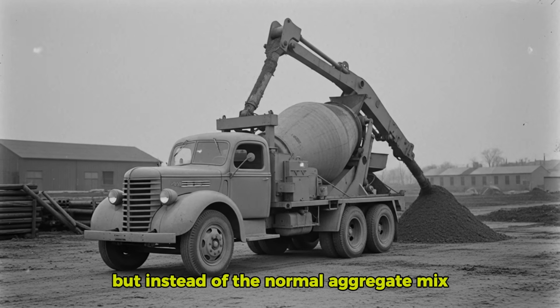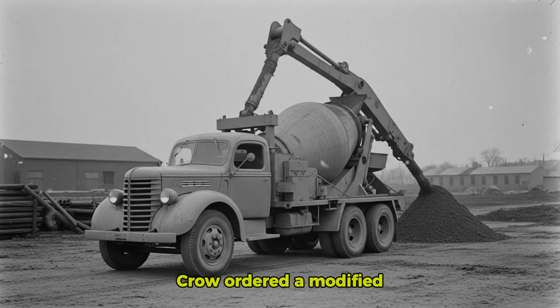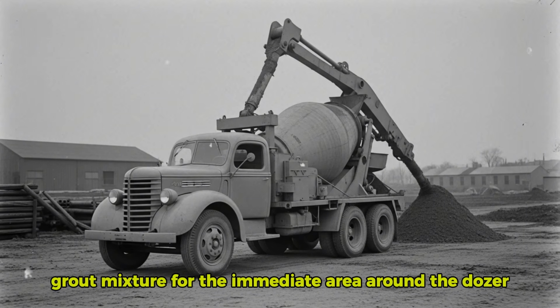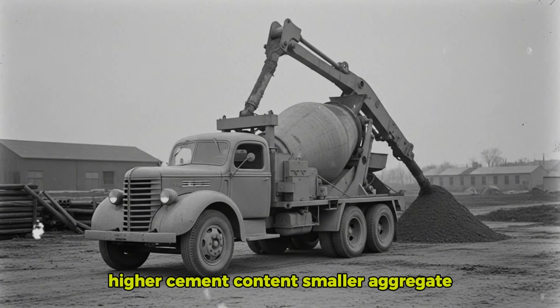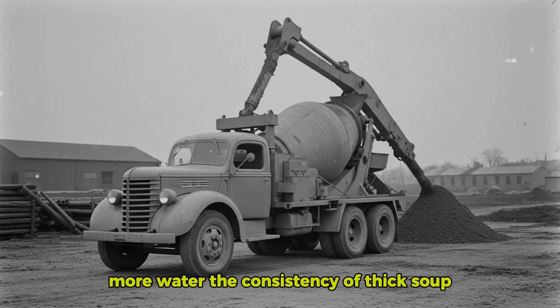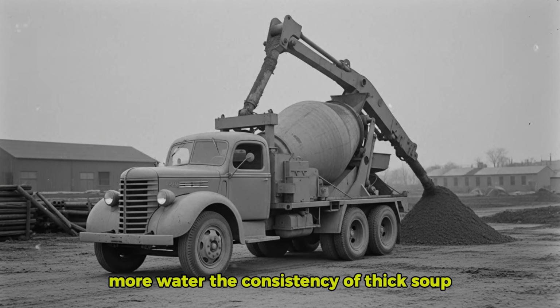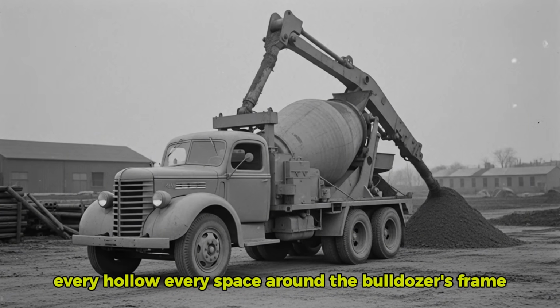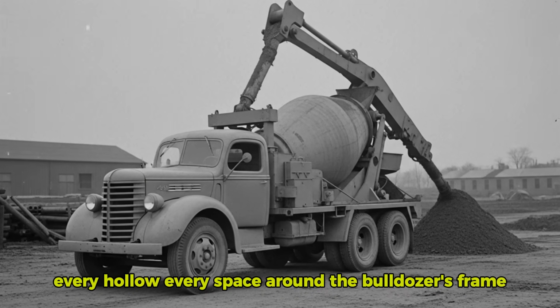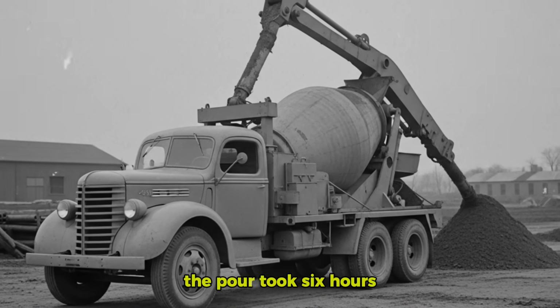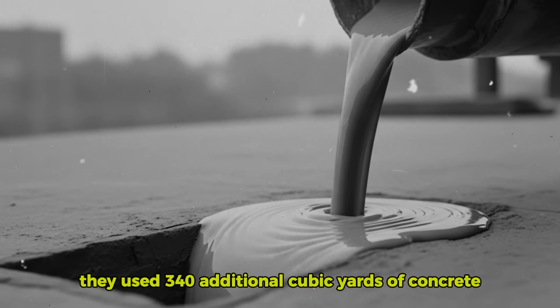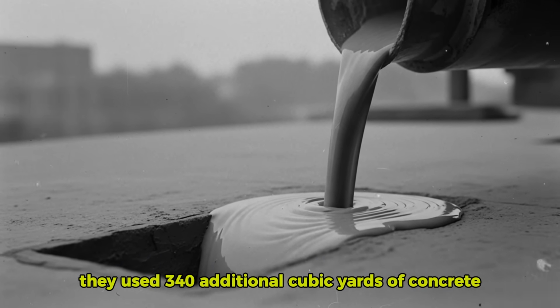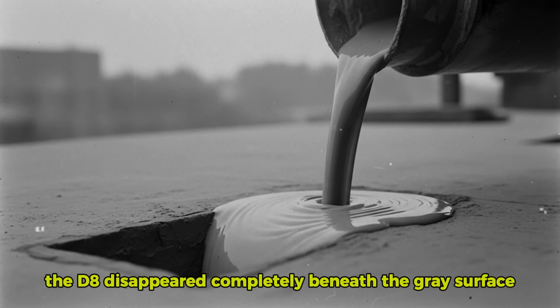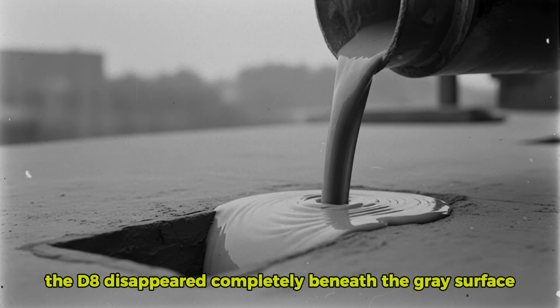But instead of the normal aggregate mix, Crowe ordered a modified grout mixture for the immediate area around the dozer. Higher cement content, smaller aggregate, more water, the consistency of thick soup. It would flow into every gap, every hollow, every space around the bulldozer's frame. The pour took 6 hours. They used 340 additional cubic yards of concrete. The D8 disappeared completely beneath the gray surface.